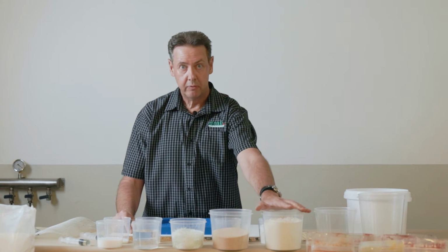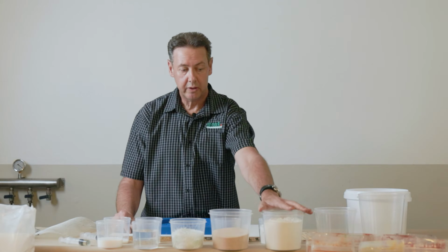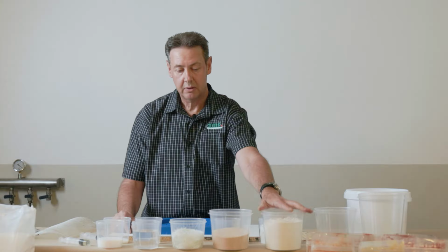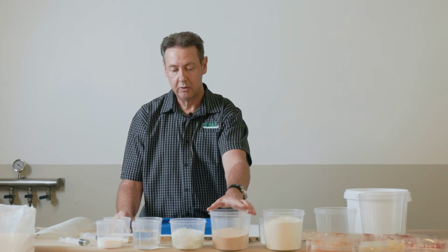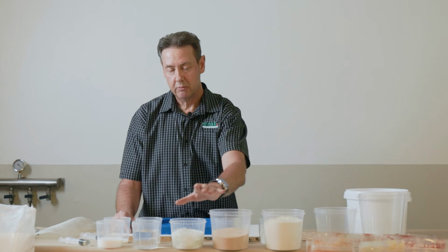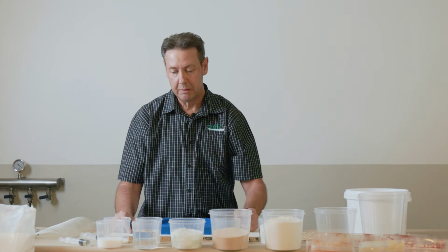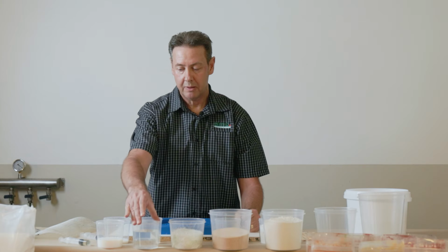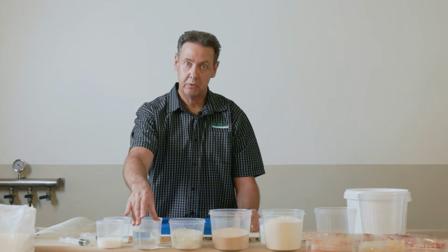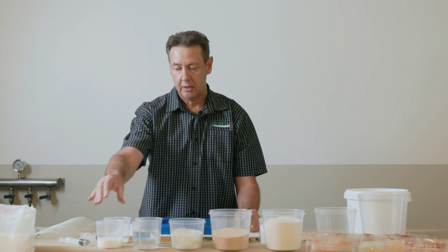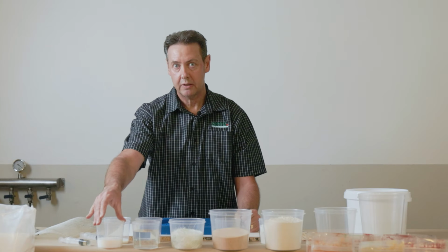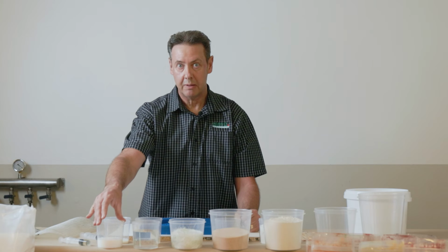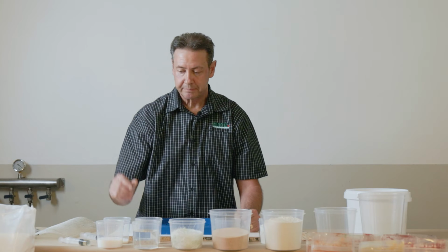The mix design that we've got, which we'll have on our website, we've got 1 kilogram of cement. We've got 850 grams of the silica sand. We've got 66 grams of our glass fiber, 270 grams of water. That proportion can be from 240 to 270 grams. And we've got 120 grams of resin here, and that can be used from 100 grams to 120 grams.